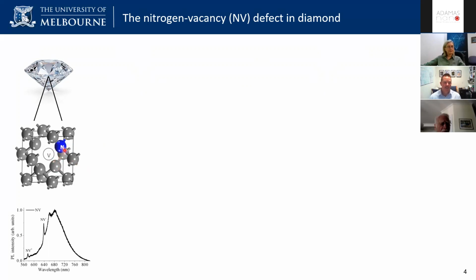So the Nitrogen Vacancy Centre is formed when we replace one of the carbon atoms in the diamond lattice with a nitrogen atom, and we have an adjacent vacancy. Now this defect can occupy 3 different charge states. So it can be a plus, a neutral, and a negatively charged state. It's the negatively charged state that we're interested in for a lot of these quantum sensing applications, although there is a lot of interesting physics happening with these different charge states as well. But for sensing and the purposes of this talk, I'm going to refer to the negatively charged state of the NV as NV from this point on.